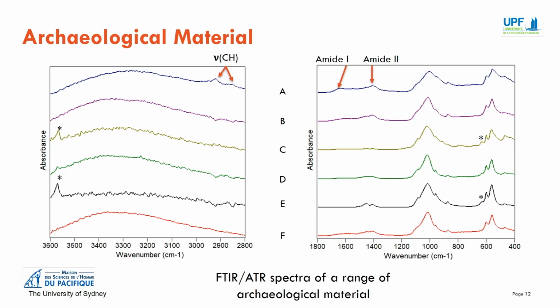The amide 1 and 2 bands are due to the presence of organic material. These bands were not present in the sample burnt at 400 degrees Celsius. However, Marquis reported these bands were present in samples subjected to temperatures below 700 degrees. The oven that was used to burn the samples had some issues with the thermostat. Future work will require a reliable furnace. Regardless of these problems, this work has demonstrated the usefulness of portable infrared spectroscopy for ascertaining the burning temperature.